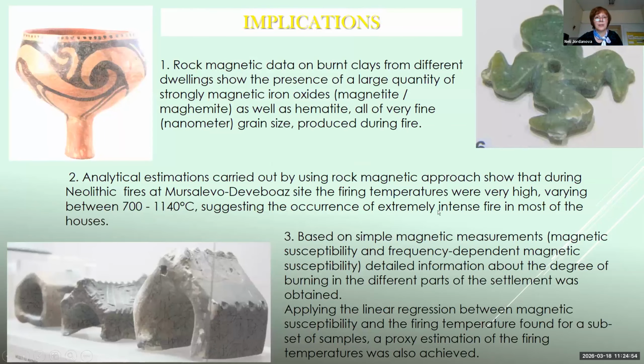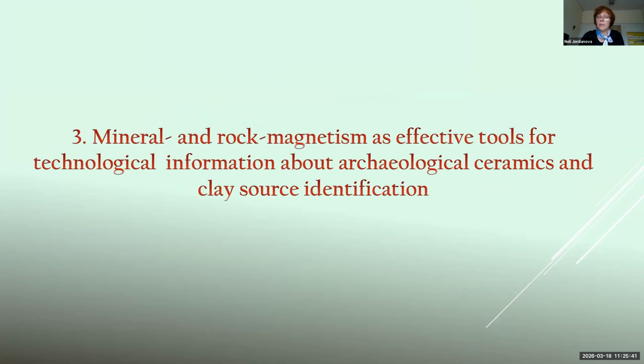So from this Neolithic burnt houses, we obtained very detailed information about the nature and properties of the fire-produced iron oxides, and they are predominantly very nanometer grain size. And analytical estimations of the firing temperatures suggest the occurrence of extremely intense fires in most of the houses. And we also get detailed information about the degree of burning in different parts of the settlement using very simple magnetic measurements. So now I will speak shortly about the archaeological ceramics and application of mineral and rock magnetic methods.